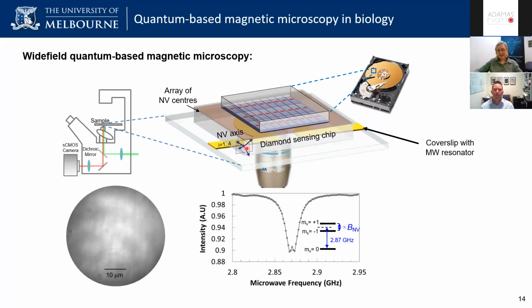Sure. So one of the key challenges is turning the nitrogen into useful NV centers. When you start getting very close to the surface, the conversion efficiency from N to NV changes a lot. Typical studies will show a conversion efficiency much less than 1%, for example. That typically means that we're putting more nitrogen into the material, which is then impacting the coherence times and the sensitivity of these experiments.